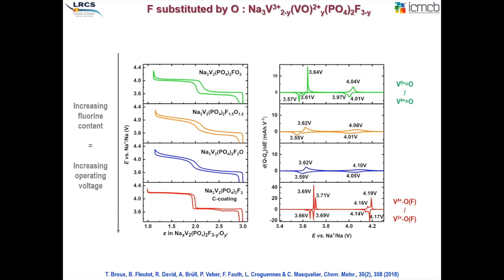You see that basically the electrochemical properties are similar, but not in detail, because you see very characteristic two-phase transformations from the stoichiometric compounds with F3, similar clearly defined two-phase transformations occur for the FO2 compounds, while we have a much more continuous evolution of the voltage versus composition when we have intermediate compositions. This is a general trend, and also what is important is that as the fluorine content increases in this structure, this increases slightly the average operating voltage from 4.04 here to 4.20, and similar for the first intercalation plateau.